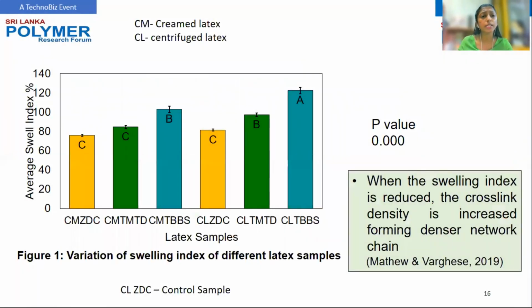Theoretically, when the swelling index is reduced, the crosslink density is increased, forming a denser network chain. ZDC has contributed to the lowest swelling index, meaning formation of the highest crosslink density, while TBBS contributed to the highest swelling index, meaning formation of the lowest crosslink density. In addition, cream latex has shown lower swelling values than the corresponding latex films made out of centrifuge latex. So, cream latex with ZDC accelerator showed the lowest swelling index and highest crosslink density.